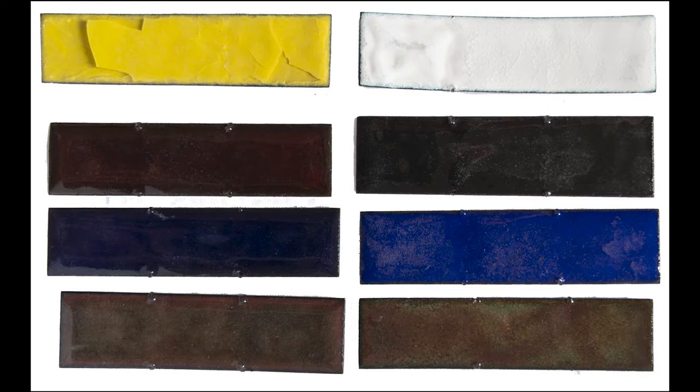After that coat, I applied counter enamel to the back to protect it from oxidization and give it more strength, then applied a second layer of color followed by clear fusing enamel. Clear fusing enamel comes in three softening points: soft, medium, and hard. By dividing the strip between those three and firing it — first upright to get it all set, then flipping it for an extended firing — I was hoping to see whether that enamel would move into those layers at different rates. Enamel is applied in very thin layers, so I could see a little in terms of how much color would come through, but wasn't able to observe a ton of movement.